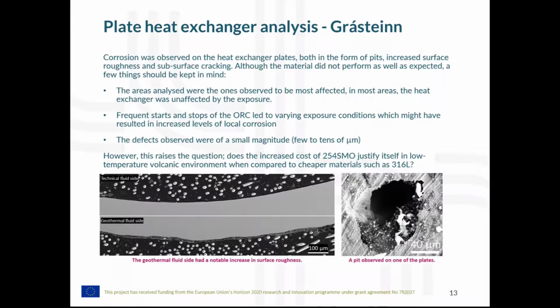And so to take the results together, for Grásteinn, we observed corrosion on the heat exchanger plates, both in the form of pits, increased surface roughness, and some minor subsurface cracking. And in general, the heat exchanger plates did perform not badly, but a little bit under expectations, we could say. So it did not perform as well as expected, given the initial corrosion analysis of the coupons.